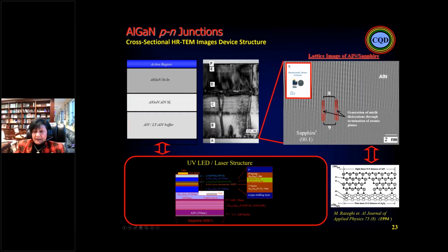But what's important? Look at here. I mentioned that all of the material that we are growing here for the LED and laser, when you do the structure, all of the layers are lattice mismatched with each other. And lattice mismatch means that it creates defects. Each defect kills the lasers in continuous wave and increases the dark current for the detector. So the material and the understanding and optimization of the material is very important.